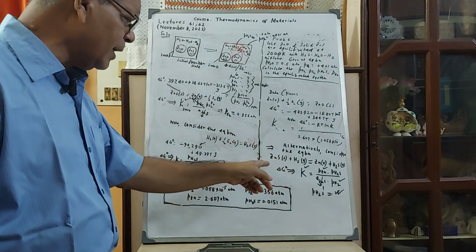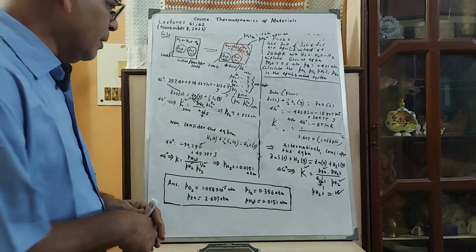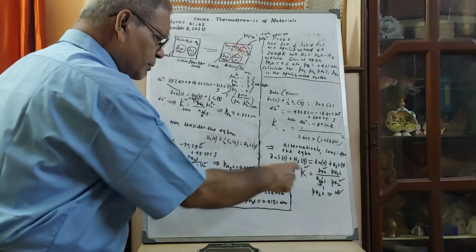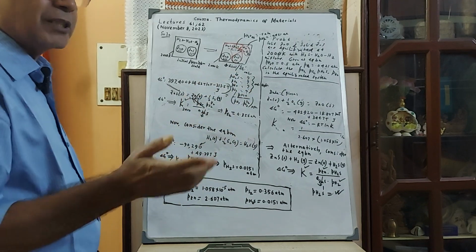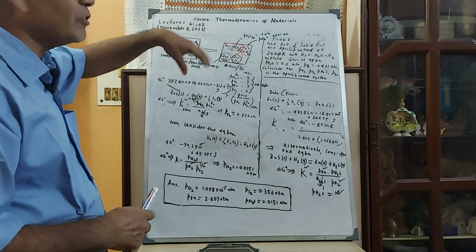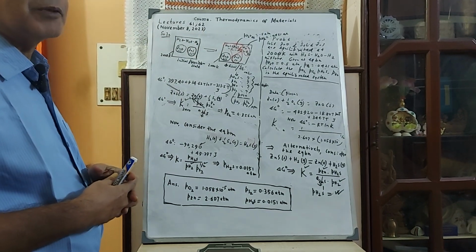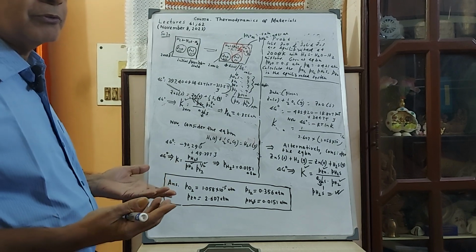If you apply the delta G0 equilibrium constant, the expression is Pzn times pH2S over activity of zinc sulfide times P hydrogen, and the activity of zinc sulfide is 1, since it is a solid. Pzn is known, pH2 is known, so pH2S can be found out, and you will get the same result. You can try this out for verification, because these are all mutual equilibria, they are compatible and in agreement, however you do it.